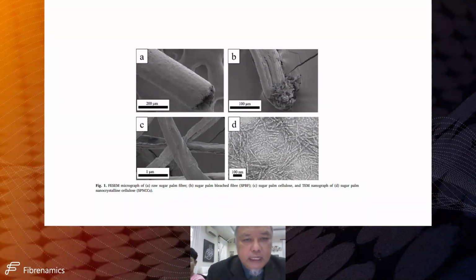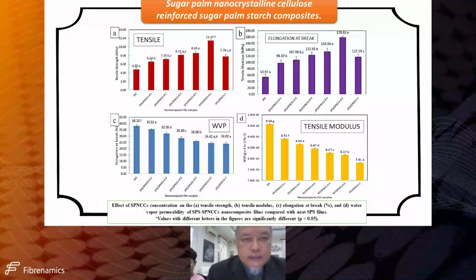This is some of the SEM result of the sugar palm bleach and sugar palm cellulose, and at the end, sugar palm nanocellulose. This is some result when we increase the amount of the biopolymer starch, so the tensile strength is improved, but the modulus in this case tends to reduce.